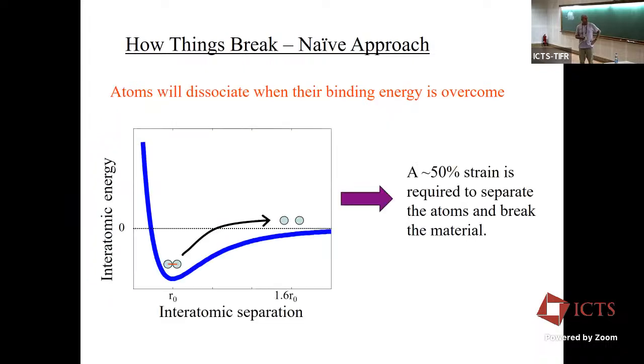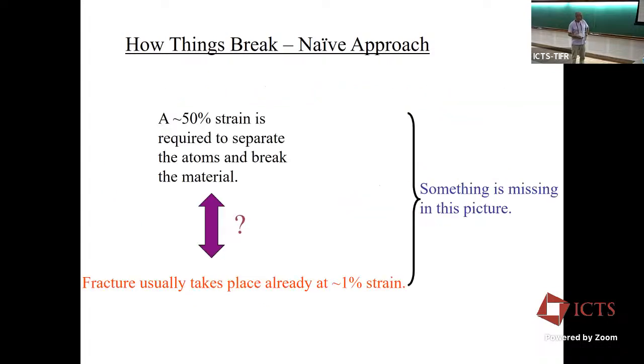Now, here's a potential between particles, atoms, whatever. And if you do the calculation, you find that approximately a 50% strain is needed in order to break something. So if you pull things homogeneously, slowly, you'll have to stretch it by 50% in order for dissociation to start. Okay, that's fine. Things can break that way. But something's wrong in this picture because usually already at a 1% strain, things fracture. So we have a 2 orders of magnitude difference between the naive approach and what happens for real.